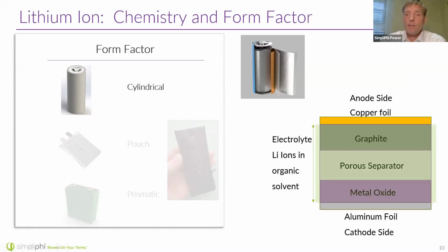The reason that I'm telling you this is that there's an electrolyte in between all of this. So the electrolyte is, think of a gel about the consistency of diesel fuel, which is absorbed into the graphite layer, into the metal oxide layer, and through the porous separator. That is the safety consideration. That is what catches fire. It's an organic solvent, and that organic solvent is what catches fire if a battery starts to burn.